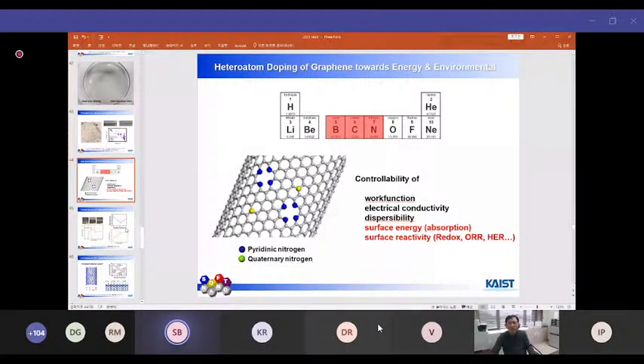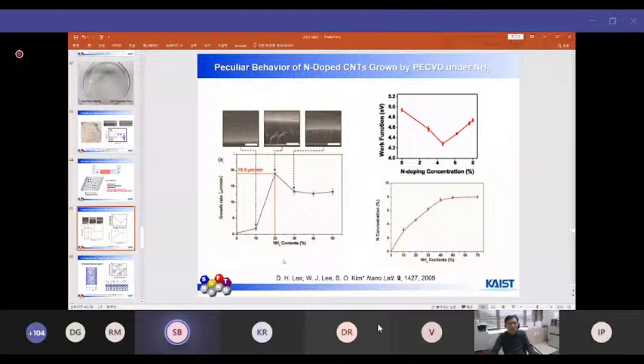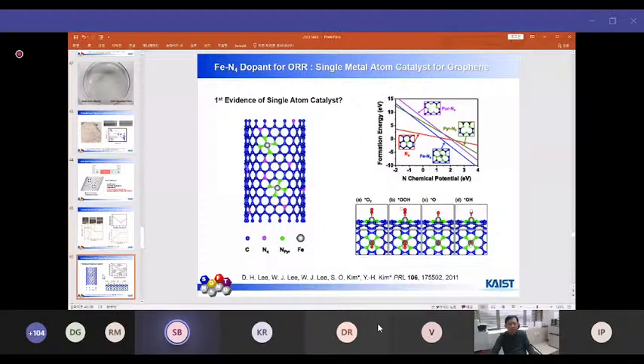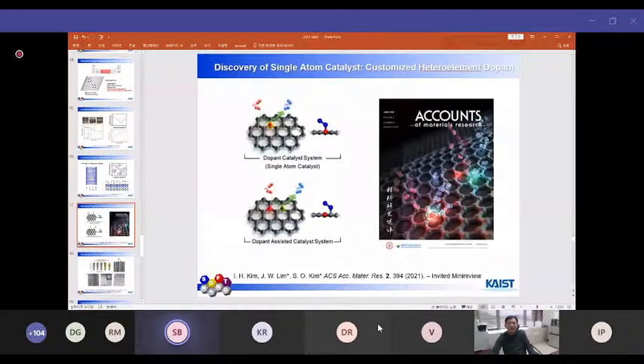Actually, we encountered nitrogen doping of carbon nanotubes during our PECVD growth. We found that there is a spontaneous formation of single atom catalyst. Iron metal was obtained from the bottom metal catalyst, and nitrogen was supplied from ammonia environmental gas. And we could also identify a single atom catalytic effect from this metal center. Our discovery of this behavior has nowadays evolved into the single atom catalyst research area. You can also find our recent review article summarizing the prospects for single atom catalysts.